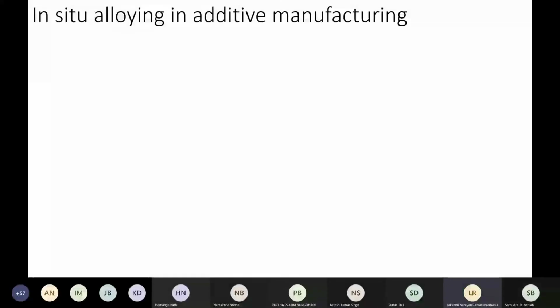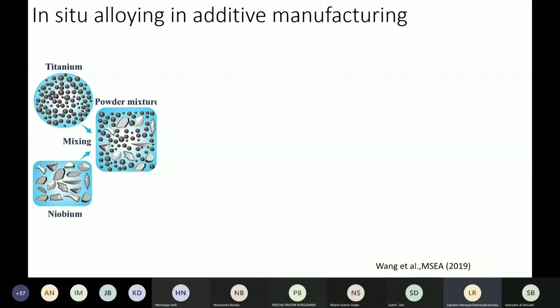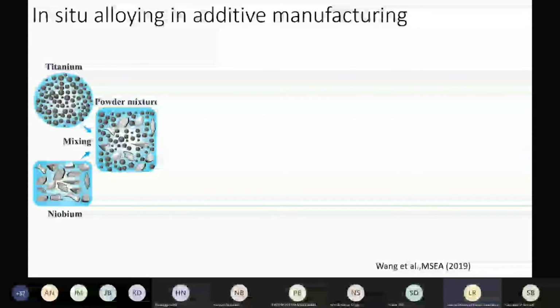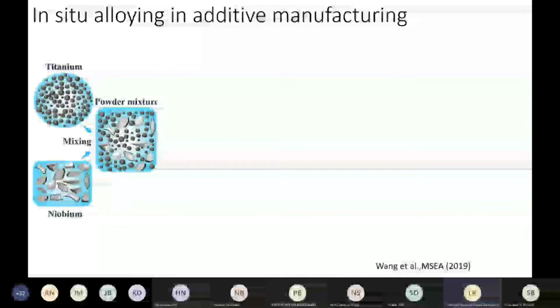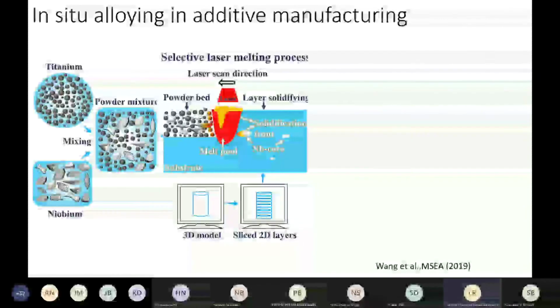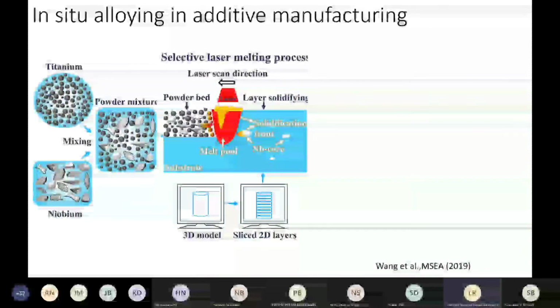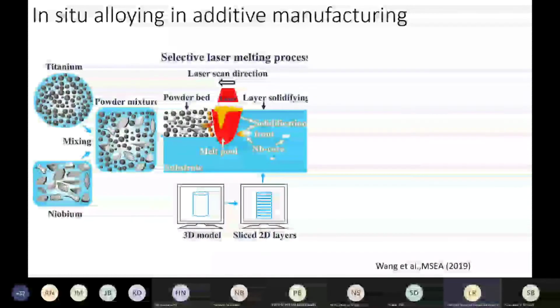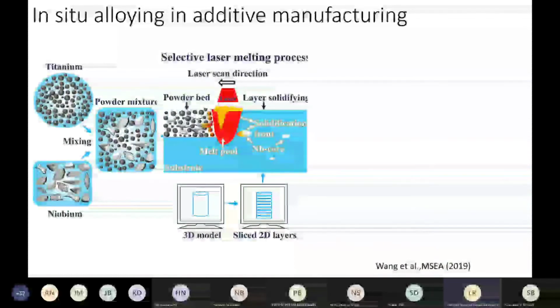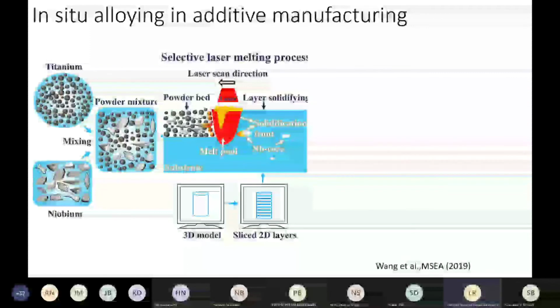And now we will do the same exercise in an in situ alloyed additive manufacturing setup. So what is in situ alloying? What we do is we use two different materials, titanium and niobium. We mix them together and we form a powder mixture. Okay. And this powder mixture is then spread over your 3D printer bed, and then a laser runs over it. What happens is that it keeps solidifying, and inherently this is probably not very homogeneously mixed, but the melt pool is created in such a way that the material homogenizes itself and then forms an alloy. So that is why it is called in situ alloying. Titanium and niobium were initially separate, but later on they become a titanium niobium alloy.